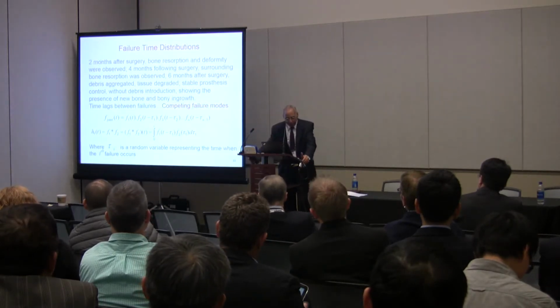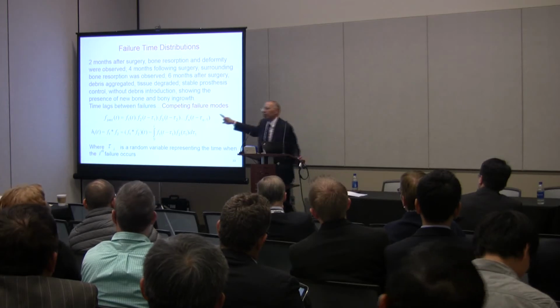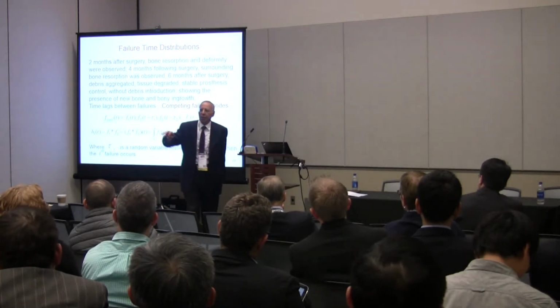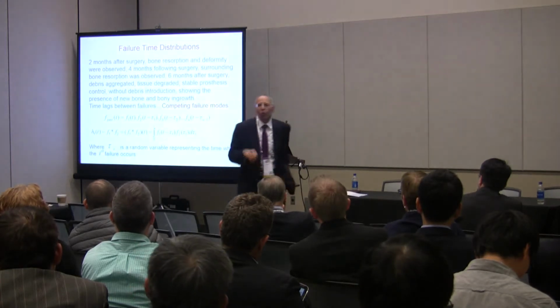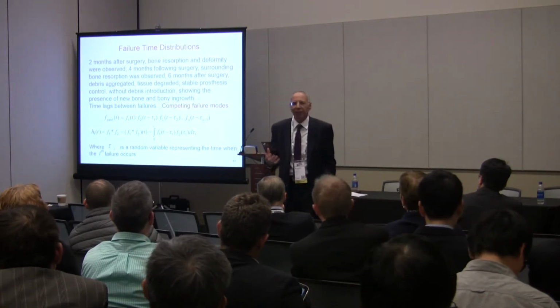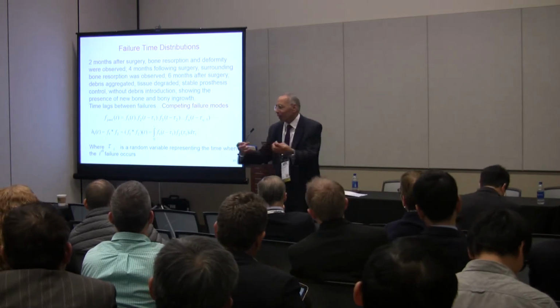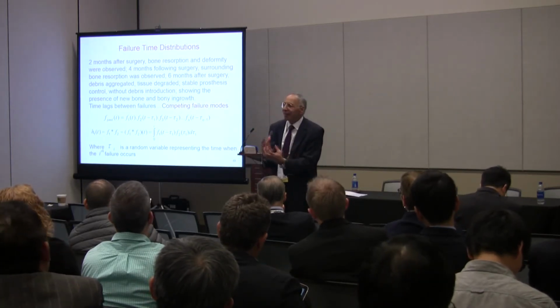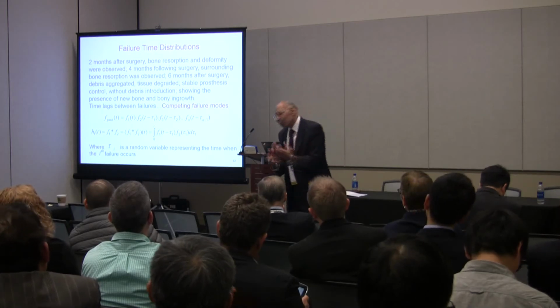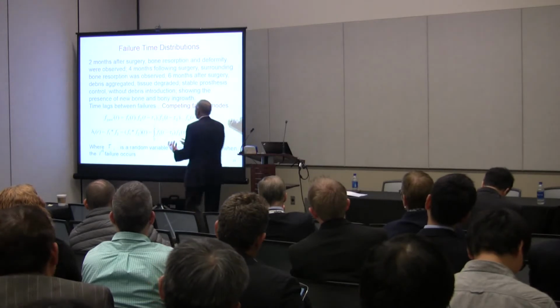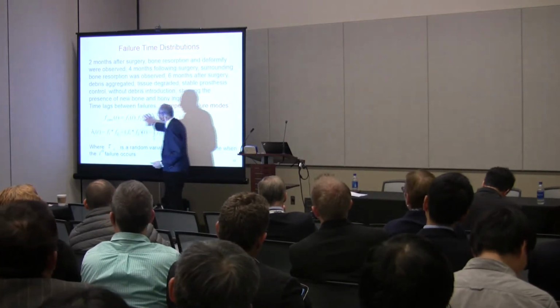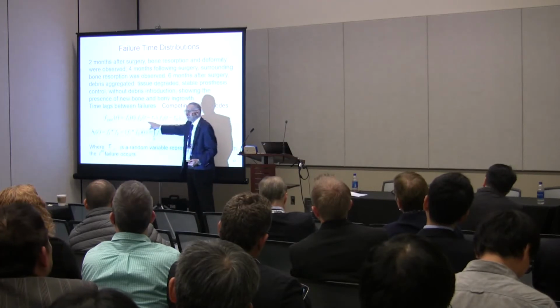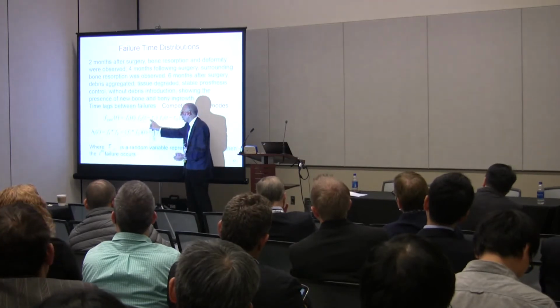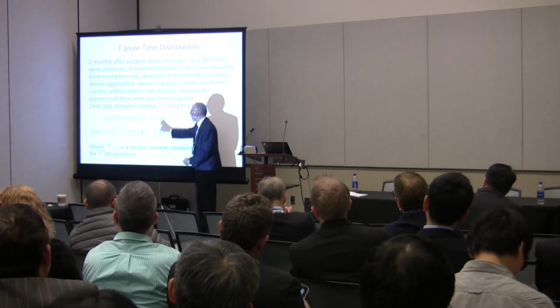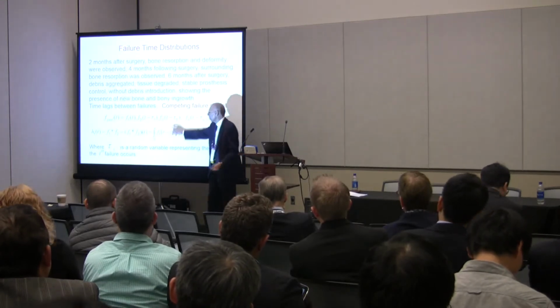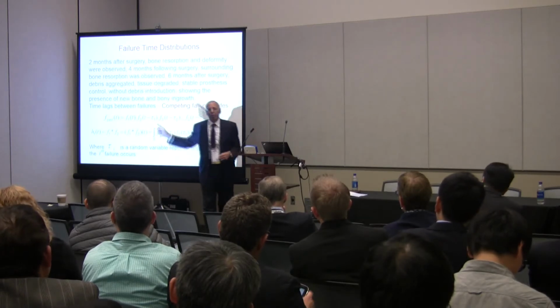So the failure time distribution is an issue, because all these failure modes don't happen at once. They happen with delayed time in between. When we do failure analysis and reliability modeling, we collect data and build the mathematical model, but if you have competing risks, where any one of them can happen at different times with a delay, there is no mathematical model today that captures the failure time distribution of the joint as a function of all these. The first one fails, the second one fails with a delayed time, tau 1. Tau 1 is a random variable. It isn't a constant value. And for F3, the third failure mode, times T minus tau 2, it's another random variable. The problem becomes complex.